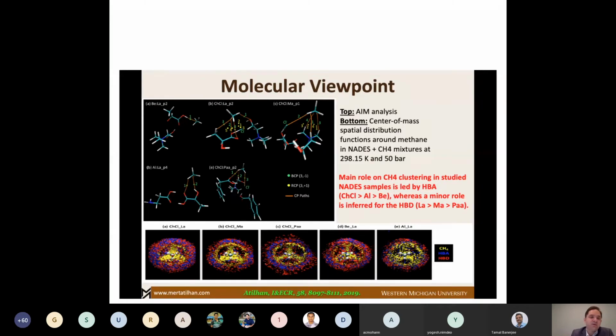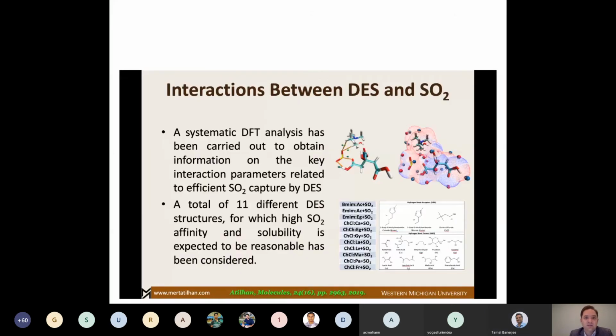Experiments tell us, okay, you get this amount of solubility and that's it. Then, by using your experience, you can start speculating on or drawing conclusions on what might have happened, but DFT really tells us what's happening in there. So, for the case of methane, we have observed that the hydrogen bond acceptor really does the heavy lifting, whereas hydrogen bond donors take the minor role while storing methane in the DES.